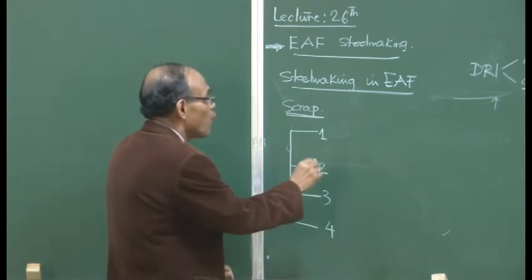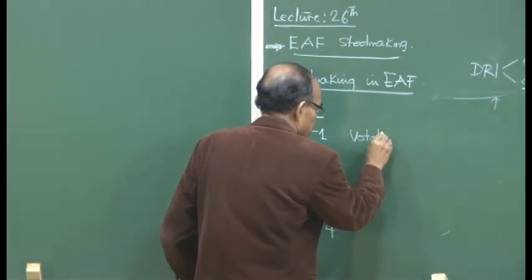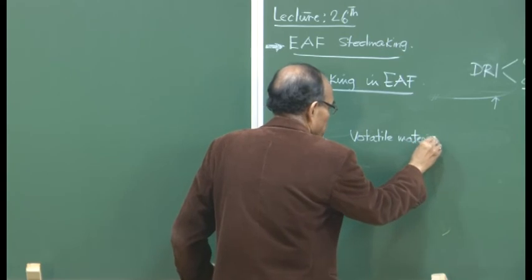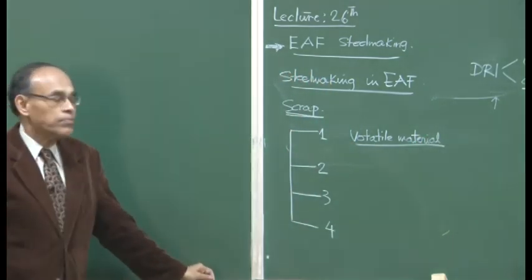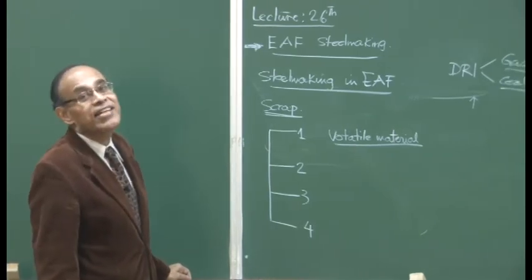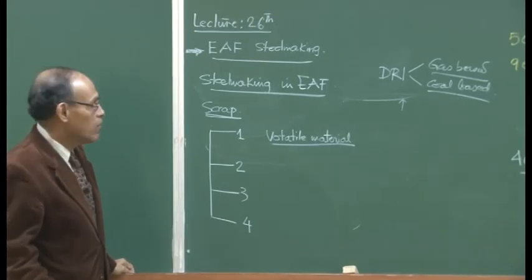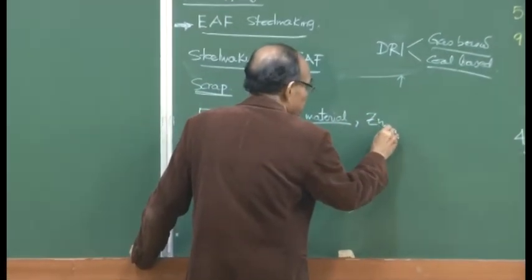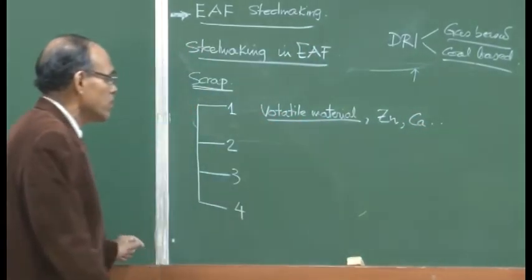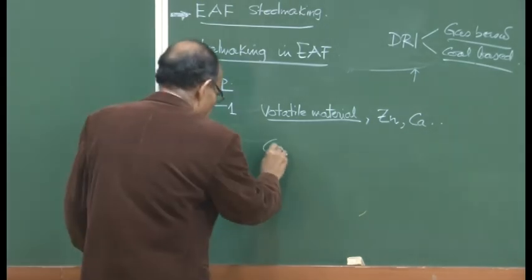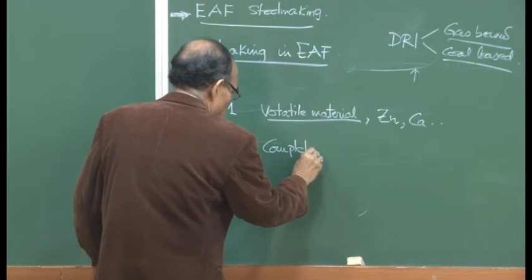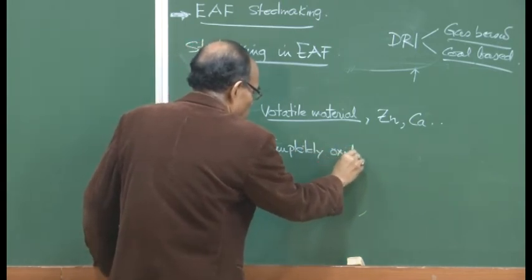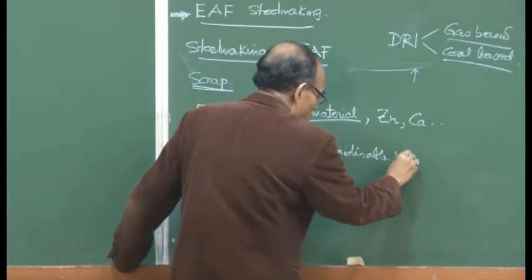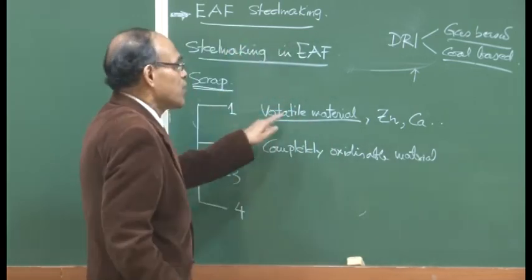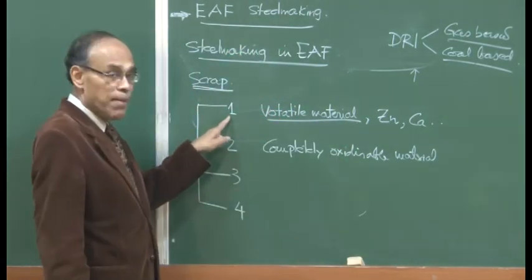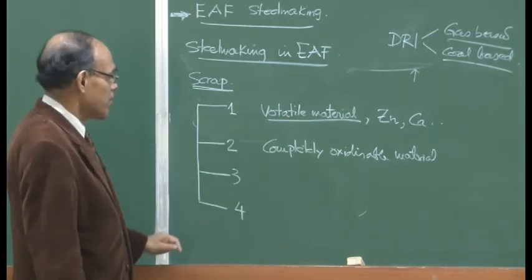One is the scrap containing volatile material, for example, completely volatile material. If the scrap contains calcium, for example, at 1600 degree centigrade, calcium is in the gas phase. So is zinc. So, zinc is a volatile material, calcium is a volatile material, and so on and so forth. Then we have completely oxidizable material. So, category 1 is scrap containing volatile material such as zinc, calcium, etc.